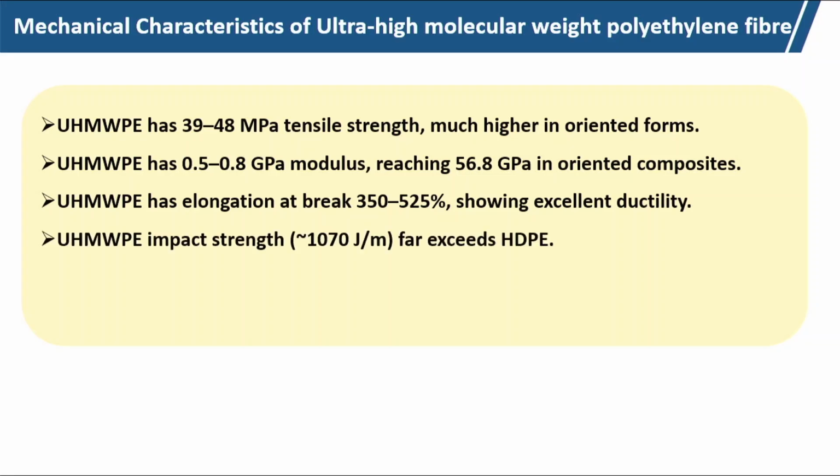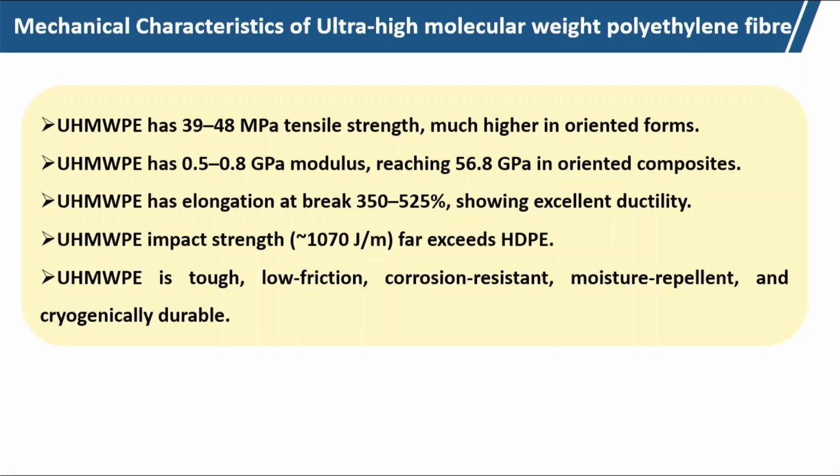Impact strength is very high, around 1070 joules per meter, far exceeding HDPE. It is tough, low friction, corrosion resistant, moisture repellent, and cryogenically durable.